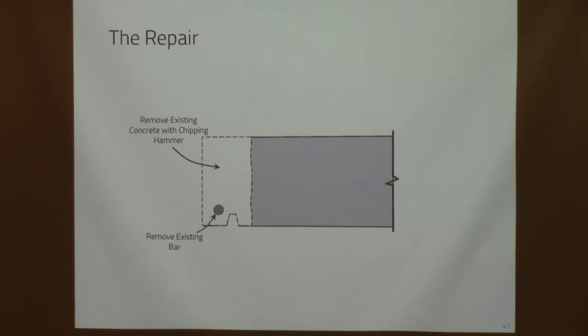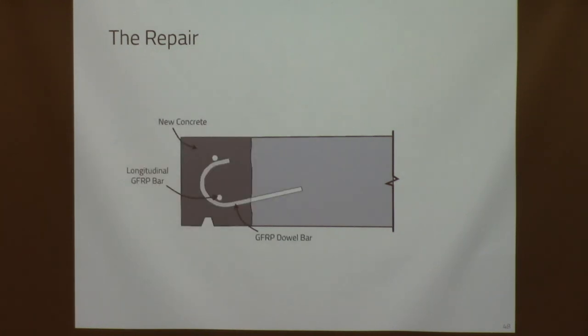There are safety precautions that can be taken to make sure that we don't have any unintended effects of the PT. So our repair was then to get rid of that bar if it did not have the right amount of cover. In some cases, we left it in place if it had at least a half inch of cover. We then used an inert GFRP bar, which is non-metallic, glass fiber reinforced polymer or plastic bar, which we had manufactured into these with 180 degree ends.